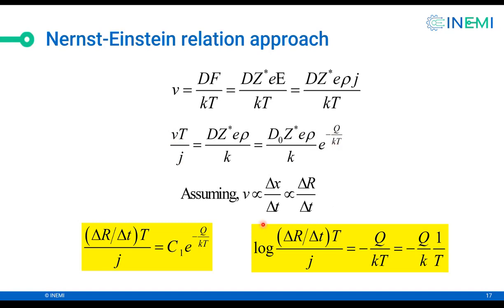And so we say that the drift velocity is proportional to dx over dt, which is proportional to dr over dt. So we replace v by dr over dt, and we put a constant c1. Then we take log on the two sides, we get this equation. So I'll show you plots of log of rate of change of resistance times temperature divided by current density is equal to minus q over k times 1 over T. I think there's a constant here which is missing, but we don't need that now.